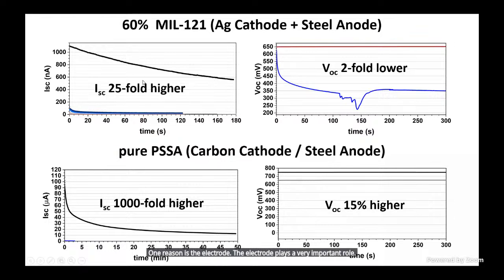So here, for example, we just changed the electrodes, and with silver and steel electrodes we could increase the current 25-fold, but the voltage decreases twofold. The second hypothesis is because of the material that we are using, polyethylene glycol diacrylate. This is not electroactive. So we tried with pure polystyrene sulfonic acid, and here we obtain an increase of 1,000-fold, three orders of magnitude.